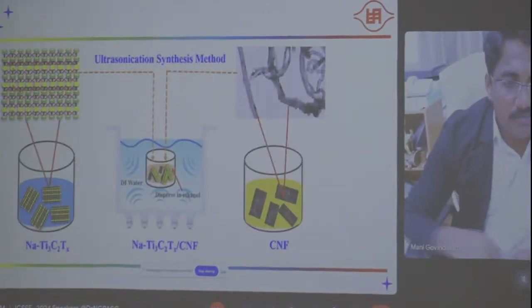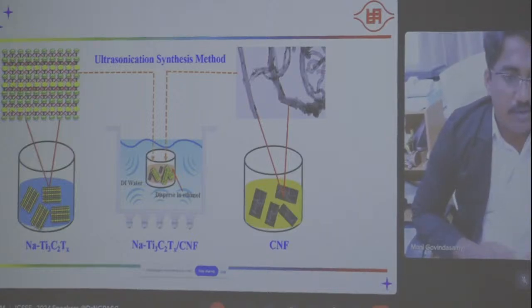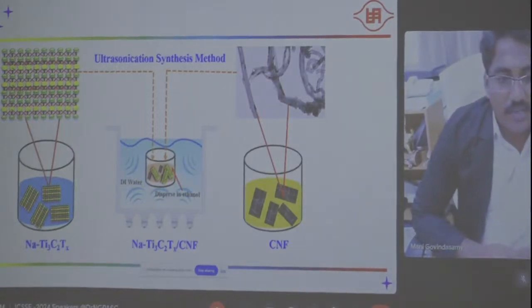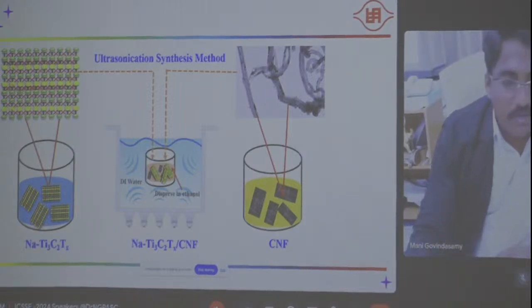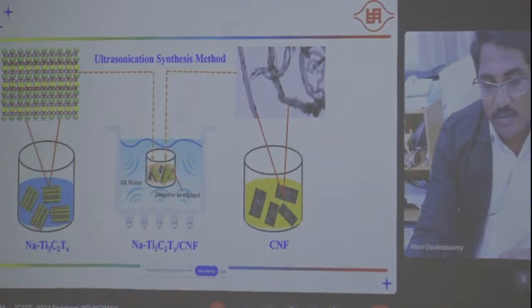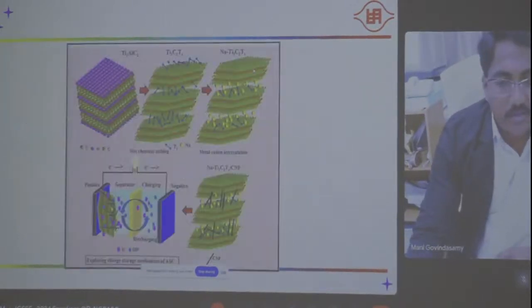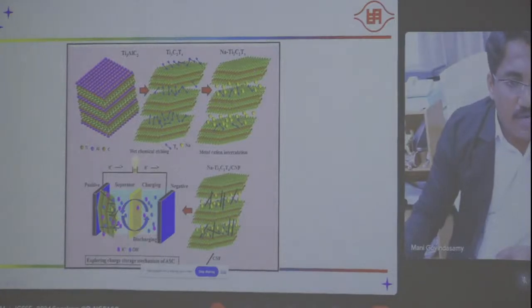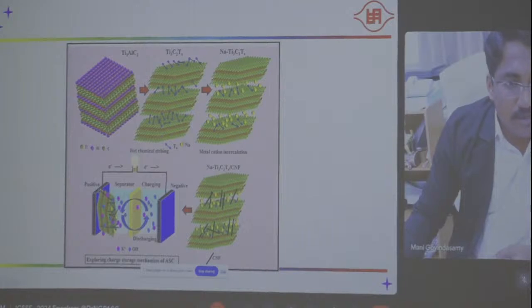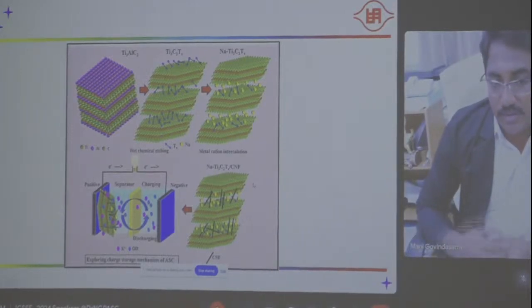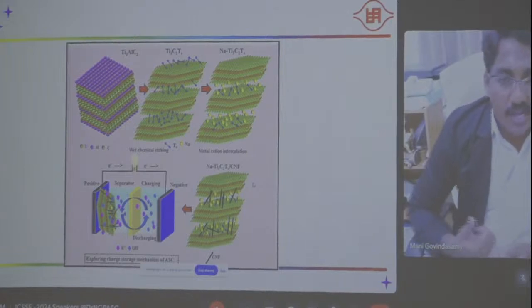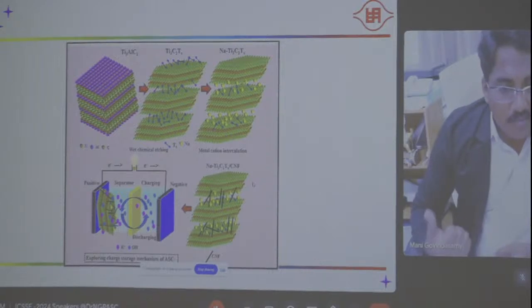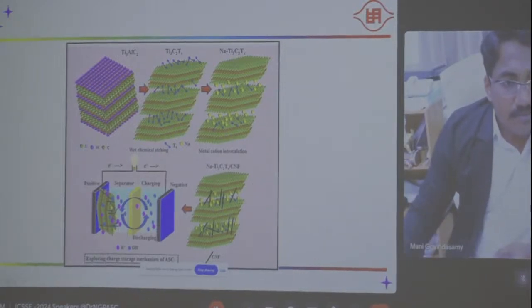So this is the synthesis procedure. We develop sodium intercalated titanium MXene plus carbon nanofiber as an electrode material. Then activated carbon we use for the other electrode. Then we make the device fabrication. Here, for the anode, the negative electrode, we use carbon materials, and for the positive electrode, the as-prepared sodium doped MXene, sodium intercalated MXene, combined with carbon nanofiber.